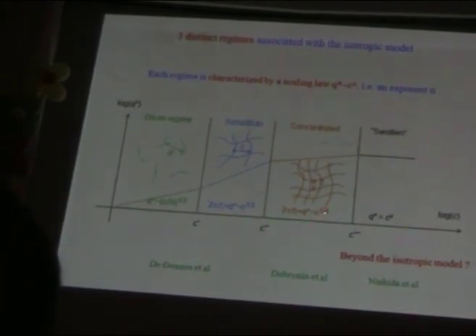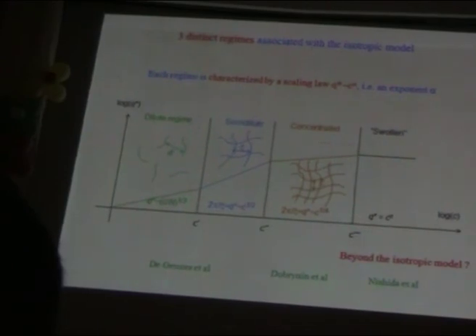So you see here, I am in the dilute regime. The Q star varies like C to the 1/3. Then I go into the semi-dilute regime. Q star varies like C to the 1/2. If you are in the concentrated regime, you have Q star which varies like C to the 1/4. I don't explain that here, but it's very easy to explain.